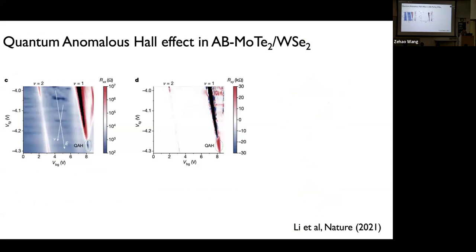So people fabricated these kinds of devices, and indeed here they measure longitudinal resistance and also Rxy as a function of filling factor and also displacement field. And the thing that I'd like you to look at is this nu equals 1 line. It's a little bit tilted. It starts with a red region that's insulating, but trivial. And at some point, suddenly Rxx becomes negligible. And at the same time, in that region, Rxy becomes more or less fixed. And that's telling you you have a new state.